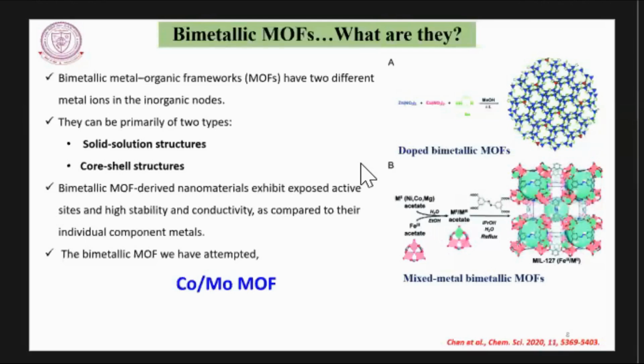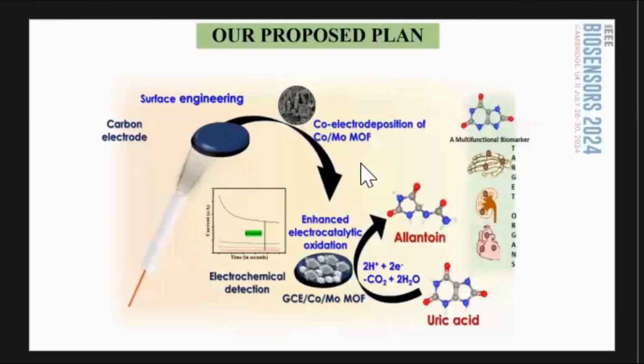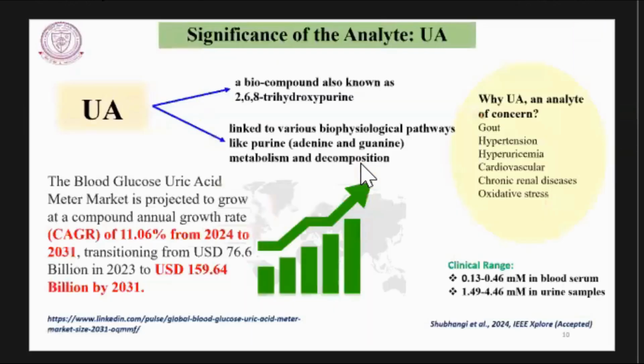So the bimetallic MOF that we have attempted is a cobalt molybdenum bimetallic MOF. Initially, we have taken a glassy carbon electrode surface that has been engineered by co-depositing it with the two metals, cobalt molybdenum bimetallic MOF, for the electrocatalytic oxidation of uric acid and its conversion into allantoin. So a little discussion on the significance of the analyte that we have chosen.